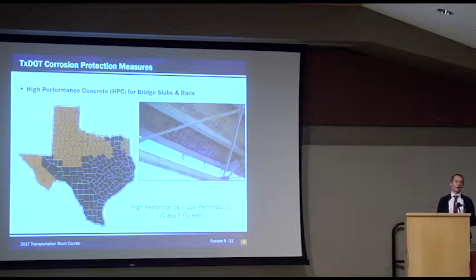Other thing we do, high-performance concrete. We produce a lot of Class F fly ash in this state, and this is a good place to put it. When I say high-performance concrete, that really just means low permeability concrete. And the idea is just like clear cover. We're slowing down the migration of these chlorides.